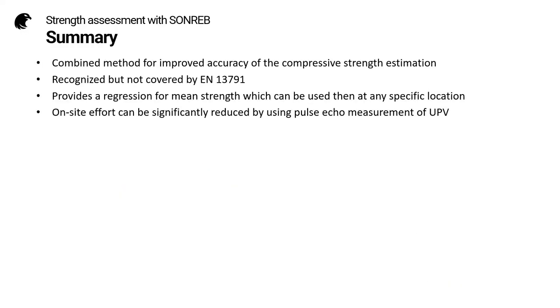So to summarize strength assessment with SONREB, it's a combined method for improved accuracy of the compressive strength estimation. It is recognized but not covered by EN 13791. It provides a regression for mean strength which can be then used at any specific location. On-site effort can be significantly reduced by using pulse echo measurement of UPV.